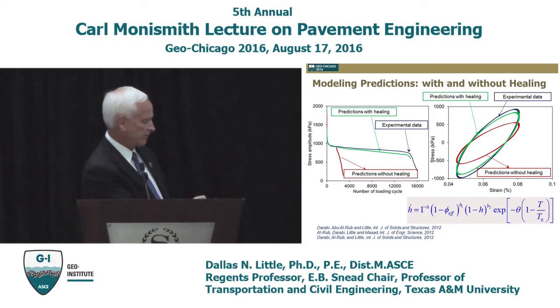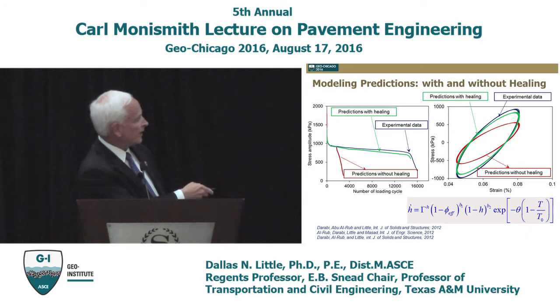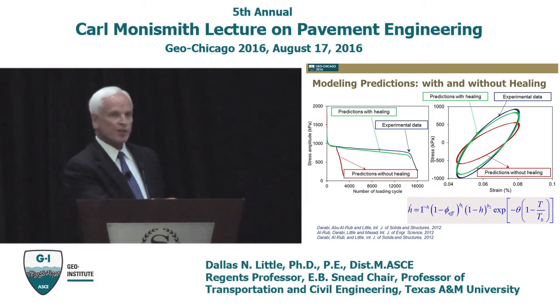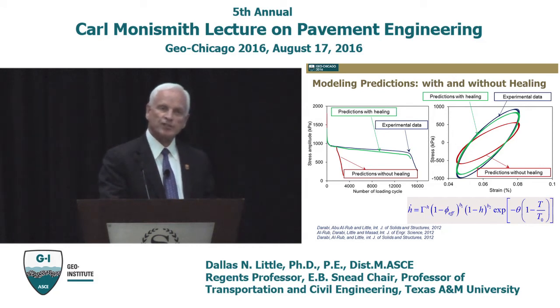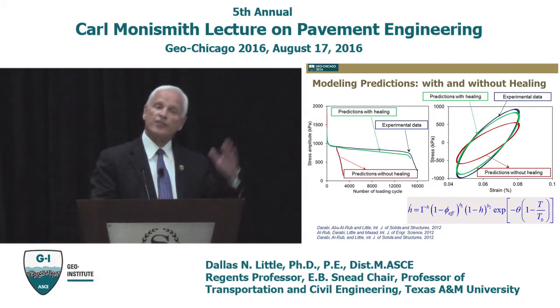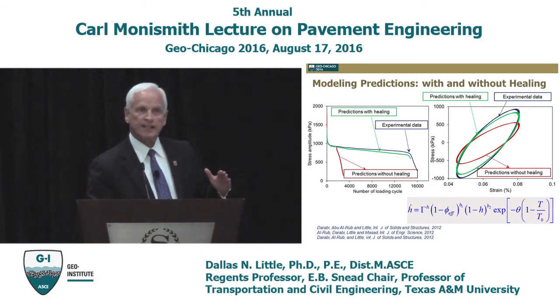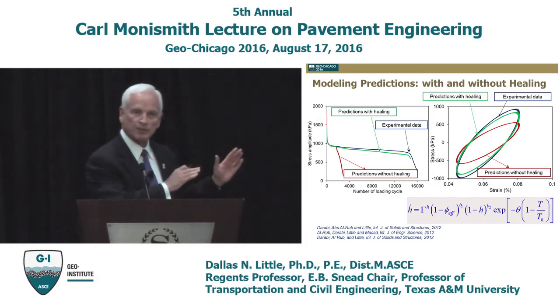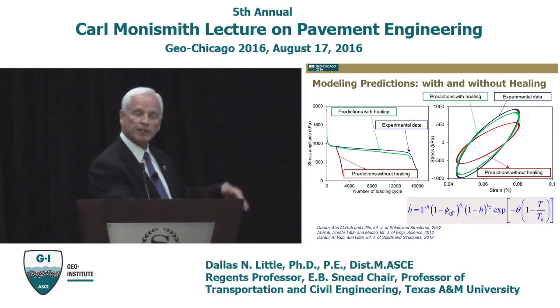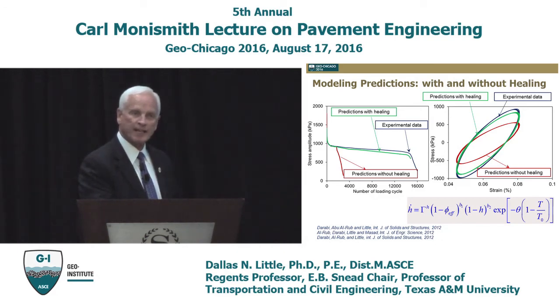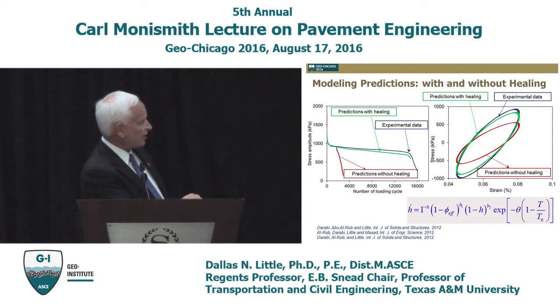power on my pointer. There we go. The healing evolution function allows us to pretty much track the experimental data, the green curve and the blue curve. So what I've done is I've looked at the blue curve and I realize that's experimental data. The green curve is now the viscoelastic, viscoplastic damage model with the healing evolution function placed into it, and it tracks the blue curve much, much better than the red curve, which is the viscoelastic, viscoplastic damage model without healing. So this is kind of what the healing evolution function looks like.